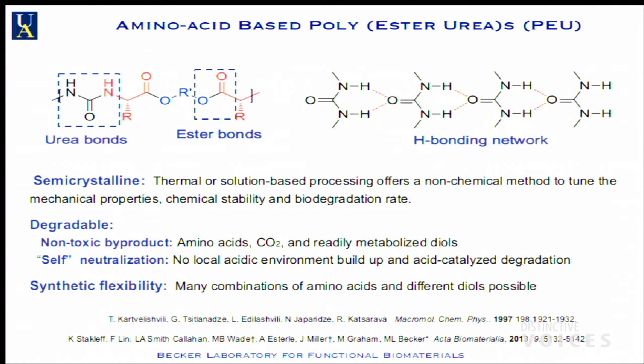After many years, we found that there's a self-neutralization effect. Like polyesters, which I showed you in the last slide, this is the most labile bond. This one breaks first. You form an acid, which leads to some of the inflammatory properties caused by the other polymers. However, you have an acid here and you have a urea-type base, so it's what we're calling a self-neutralization phenomenon. We've been in 6 different animal models, vascular, bone, neural, and never seen inflammation, and that's where we're left, and we're trying very hard to prove that.